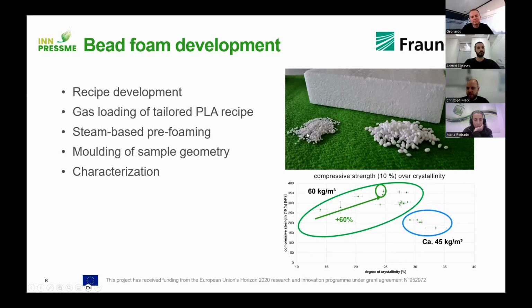Here you can also see the single product throughout this processing chain. So we have the gas-loaded beads, which can be expanded a little bit like popcorn in the end. Then we have the foamed beads, and these foamed beads are then molded together with steam to such a part. In the end, in this case, it's a sample geometry.